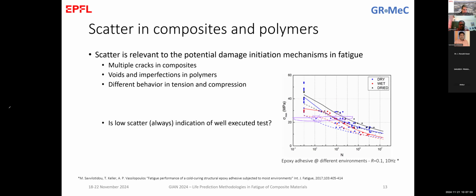So to close this short discussion here, for me, low scatter is good. However, sometimes low scatter indicates not well executed tests, but the opposite. I will close with a small example. We might have low scatter because all the specimens are failing in the tab. They're failing at a specific load. So then all the specimens will be somewhere in fatigue life for a specific stress rate and for a specific stress amplitude. But this doesn't mean that these data points are valid and should be used in the analysis. So again, to summarize, get your data, but then be critical with your data and use only those data points for which you have a reason to believe that they are reasonable and valid.